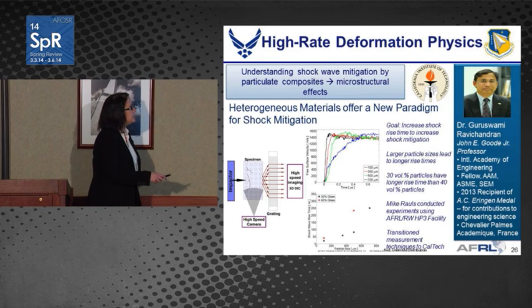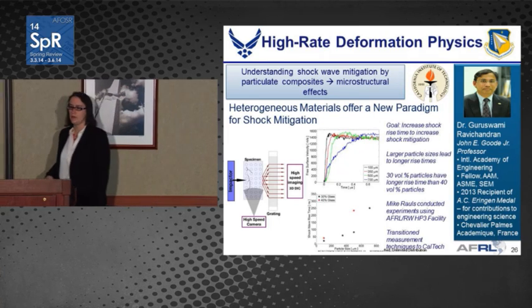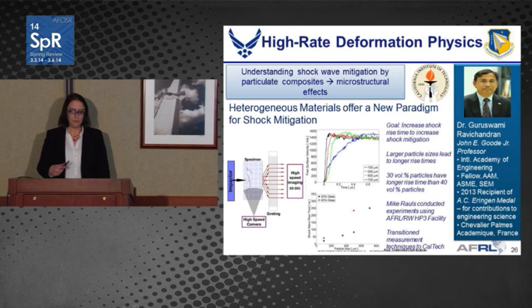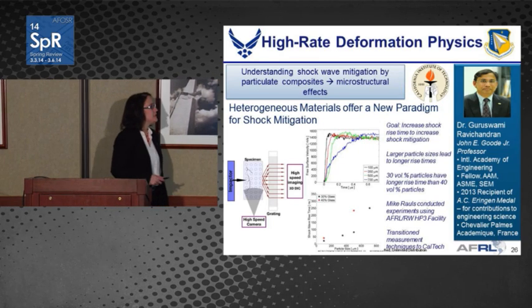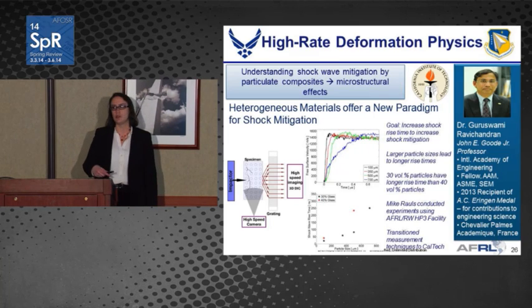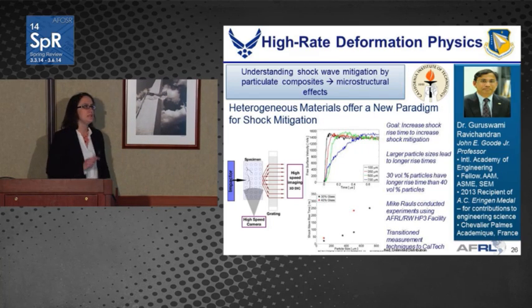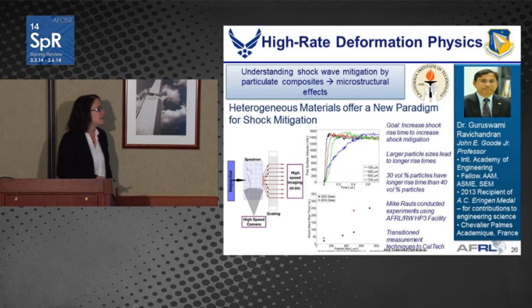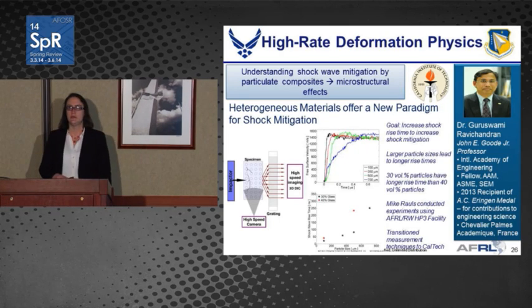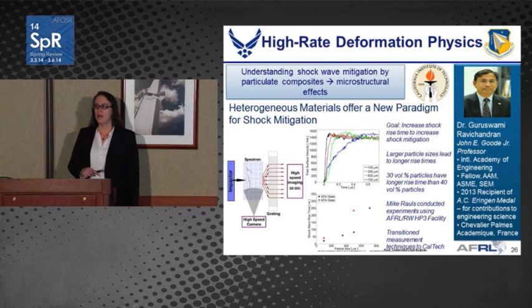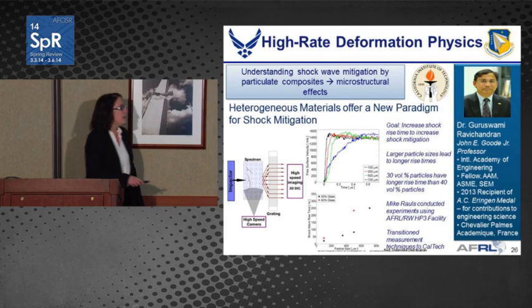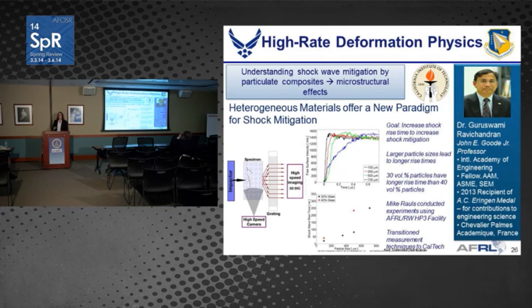So here you can see some of the results where they had 3 different particle sizes, and then as they went to the largest particle size, they saw a dramatic increase in the shock wave rise time over the other materials. So they're really starting to understand how that microstructure can control the shock wave rise time. But I think what is even most interesting about this research is that these experiments were actually conducted using the HP3 facility, high pressure particulate physics, at Eglin Air Force Base and the Munitions Directorate by graduate student Mike Rawls over the summer through an exchange through the Center of Excellence.